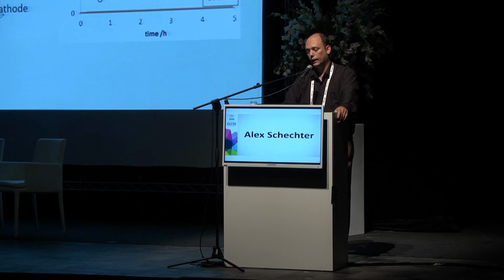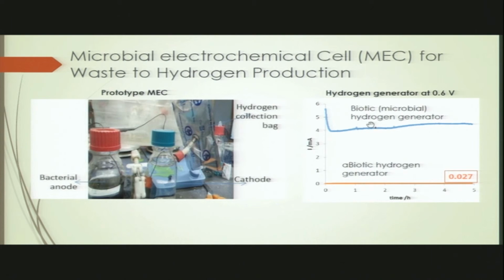You can see here at 0.6 volts, this is a biotic device that contains microbes at the anode, whereas here is an abiotic device without these bacteria, and there is a significant increase here, about 2 orders of magnitude. There's still work to do, but it is very encouraging. By the way, electrolysis, just for example, takes place only above 1.2 volts. So here we have a major advantage.